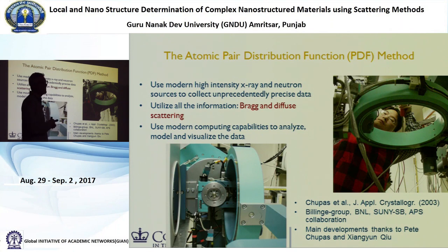So the accelerating voltage was something like 80 or 100 kilovolts. Copper K-alpha is 8 kilovolts, so it's 100 times more energetic than copper K-alpha radiation. And we took a 2D detector, which had a large area, and the sample goes here, and we simply pushed the detector as close as we could to the sample. So two things happened. The short wavelength X-rays took the whole reciprocal space and squeezed it in the forward scattering direction. And then the 2D detector pushed very, very close to the sample gave us this large acceptance angle. And we were able to get a complete diffraction pattern in one shot.